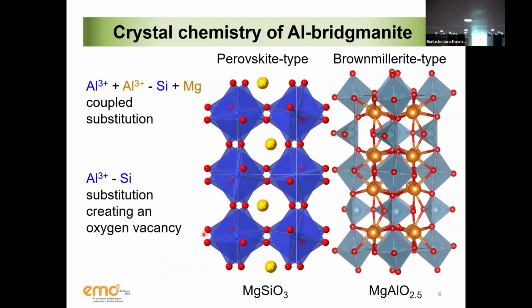However, in some places in the mantle you can even have what is called the oxygen vacancy mechanism. So you substitute only silicon on the octahedral site, and you create an oxygen vacancy in order to balance the charge. And then this is the brownmillerite-type structure, which doesn't exist in the lower mantle, but it's just to show you what you may expect when you do this kind of oxygen vacancy substitution. So what we were after is, of course, you have these two mechanisms. Which one is important when? That's what we want to understand.